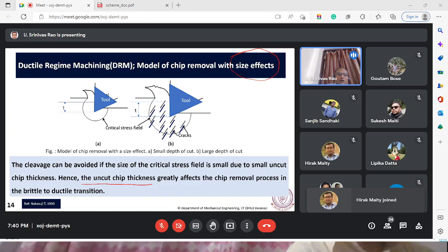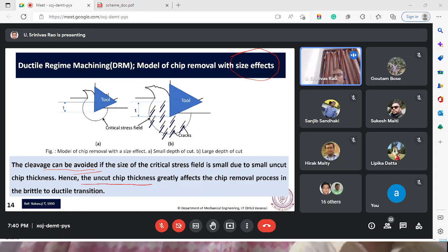Here the main issue is that the uncut chip thickness greatly affects the chip removal process in the brittle to ductile transition. In fact, the first preliminary phase is the ductile phase. Then when you further increase the depth of cut, we have the brittle phase. So we need to have the uncut chip thickness in such a way that these cleavage planes are avoided. This is a publication of Nakasuji in 1990, who gave some inputs for these activities.